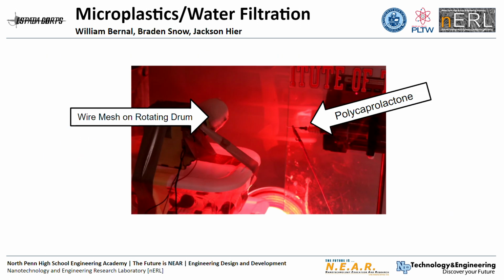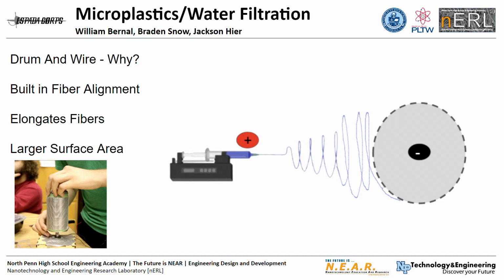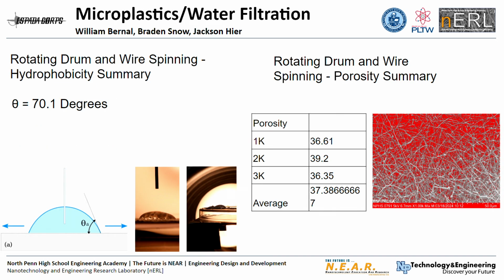And the next type of spinning we used was drum spinning. This involved taking wire and wrapping it around a rotating drum. The rotation of the drum allowed for the fibers to be stretched around the wire, adding for a greater alignment, which we can see affected our data later. And additionally, it had the same benefits as the wire spinning with the pseudo alignment and the greater conductivity. Unfortunately enough, these filters were not hydrophobic. And specifically for drum spinning, its porosity was even higher than the wire spinning before.